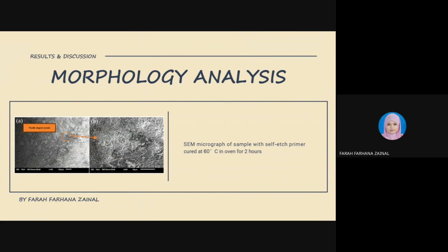So it reduces the presence of unreacted fly ash, promotes the formation of dense gel matrices, and enhances the binding of quartz powder. So these improvements suggest that geopolymer coatings cured at elevated temperature have the potential to exhibit superior properties in terms of adhesion, durability, and also corrosion resistance compared to those cured at ambient temperature. So this is the best compared to the others.